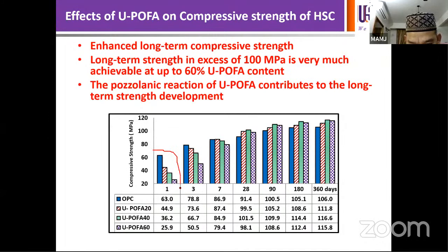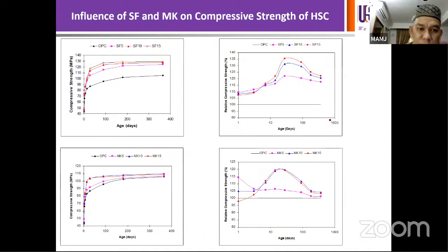If you can see the trend at early age of 1 up to 7 days, for example, the concrete containing POFA, in particular those with higher POFA content, exhibits lower strength, but not at long term here. At 1 year, the concrete containing 40% U-POFA shows the highest strength in comparison to the other mixes. All right. So in the case of silica fume and metakaolin here, we can see in general, both materials, okay, contribute towards higher strength of concrete in comparison to the control, in particular for the case of the silica fume concrete. So based on this relative strength plot, we can see, all right, even at 1 day, there is close to 10% increase in strength in comparison to the control concrete.